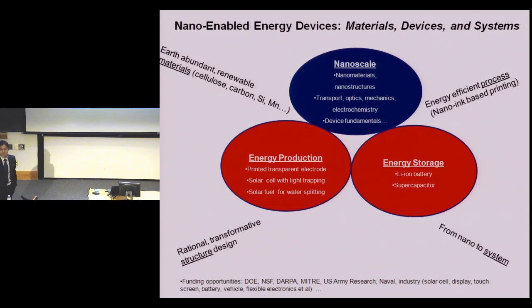Yes, it's fully flexible, because in the end, especially if we're talking about the cellulose-based transparent paper, you cannot tell whether a fiber is nanotube or cellulose anymore, because they are almost identical in size and shape as well. They are fully entangled with each other. If you don't measure the resistance, you cannot tell whether it's cellulose or nanotube. So if we can make a nanotube film transparent, there's no reason that we cannot make cellulose transparent. And cellulose never absorbs the light, whereas nanotubes actually absorb the light.